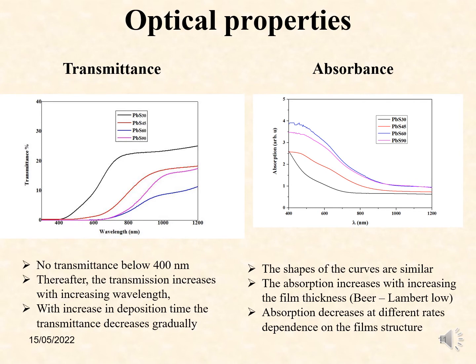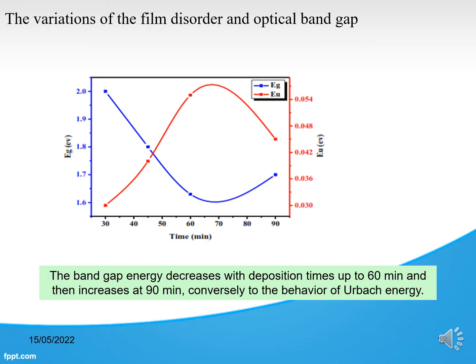The absorbance. The shapes of the curves are similar. The absorption increases with increasing film thickness. Absorption decreases at different rates, depending on the film structure. The variations of the film disorder and optical band gap. The band gap energy decreases with deposition time up to 60 minutes and then increases at 90 minutes, contrary to the behavior of the Urbach energy.